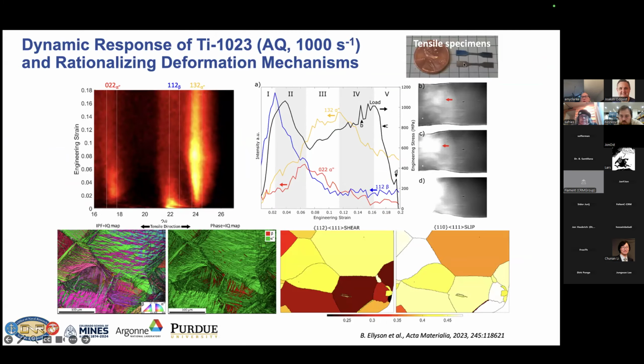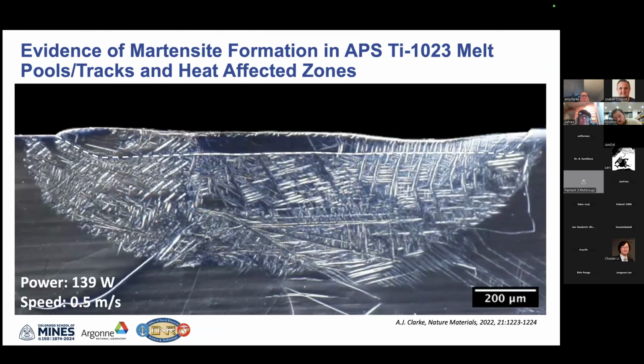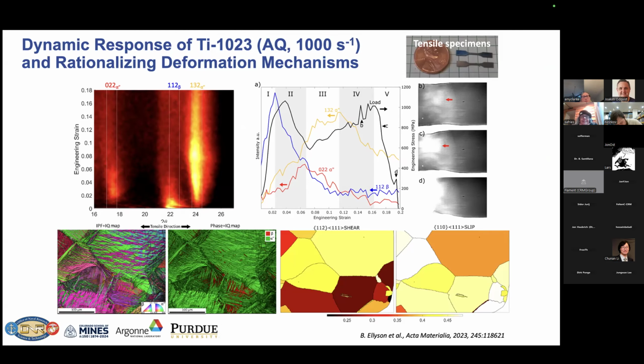So this is some work we did doing ultra-fast diffraction at the Advanced Photon Source of these little tiny tensile bars, pulling them apart at 1,000 per second with Kolsky. What's neat about this is we can actually monitor the phase transformation. So here in blue, we're monitoring the reduction of the beta phase and the increase of the martensite that forms with deformation while we're ripping these samples apart. This was in Ti-1023, I should say.